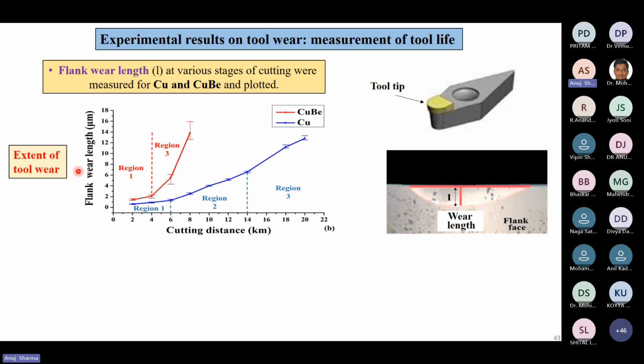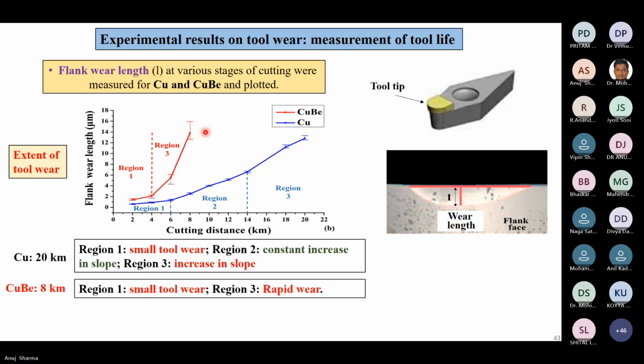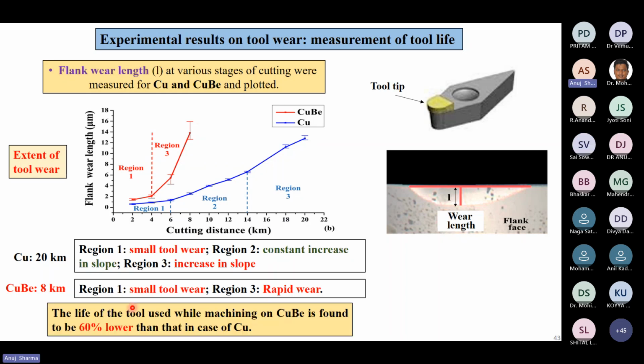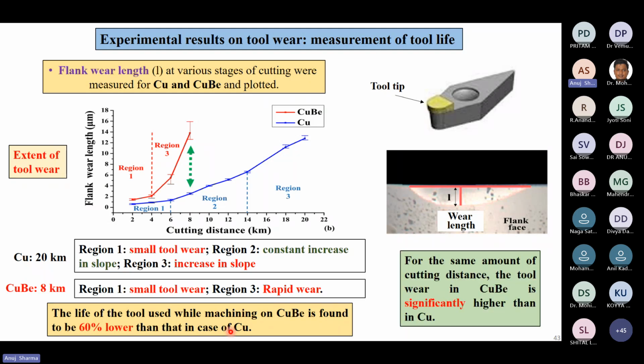When I plotted the wear length with respect to cutting distance, it showed the extent of tool wear. In copper, it almost covered more than 20 kilometers of cutting distance. But in the case of copper beryllium, the flank wear was very dominant. It can be identified by 3 regions in copper, but in copper beryllium there were only 2 regions, because after the initial wear there was a catastrophic amount of wear in the tool used on copper beryllium. It was found that the tool used on copper beryllium has 60% lower life than that used on copper.